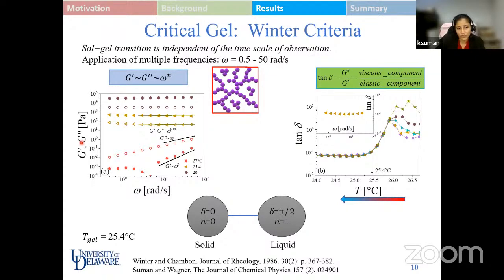In the left graph, we show the evolution of G prime and G double prime as a function of frequency at different temperatures. At 27 degrees, we can see that G prime follows an omega squared dependence and G double prime follows an omega dependence, which suggests liquid-like behavior of the suspension. With a decrease in temperature to 25.4, we have identical power law dependence of G prime and G double prime. With a further decrease in temperature to 20 degrees, solid-like behavior is dominant, where G prime dominates G double prime throughout the region. The same behavior can be plotted in terms of tan delta, which is the ratio of the viscous to the elastic component of the viscoelastic material.